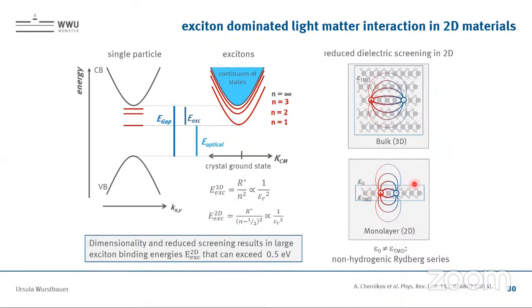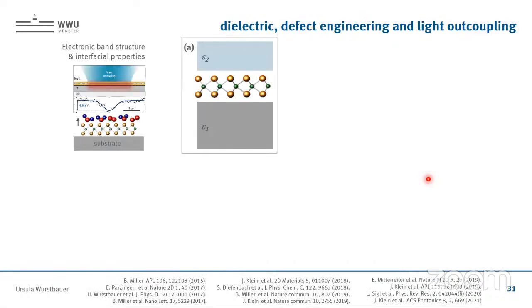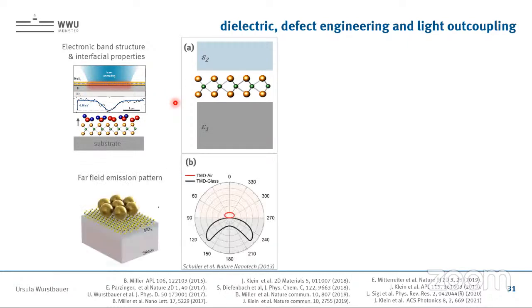So overall, due to the fact that these 2D materials are sensitive to the environment, that they can be exposed to the environment, and that the dielectric environment can be changed, we have a lot of different things that can be, let's say, tuned. We can tune the single particle properties, the energetics, which is shown here. If you have the 2D materials on a metal, you can change the energetics by enhancing the coupling to the metal. Or just for sensing, if you have, for instance, water molecules on top.